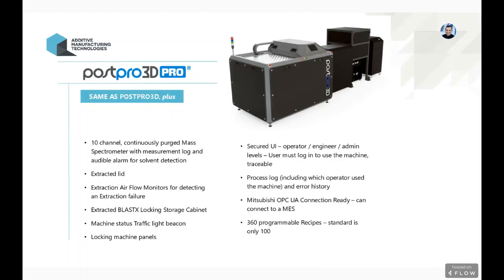And it's a closed loop system where we can control the flow of all these vapors within the chamber, so that we can treat the outer surfaces of a part in a very homogeneous way, as well as the inner cavities and the inner surfaces, which is very, very different, and it's unique to the PostPro3D. There are no technologies out there today that can tailor a very specific RA value. So you have a surface roughness RA value coming out of the printing, whether it is FDM or SLS or multi-jet fusion. PostPro3D will allow you to tailor a specific RA value because of the ability to control all